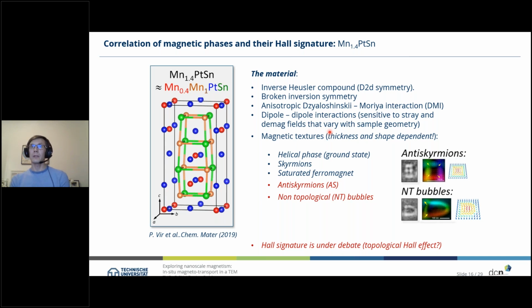So what makes it interesting for us, it hosts anti-skyrmions as well as non-topological bubbles, and especially the anti-skyrmions. For that, the Hall signature of these anti-skyrmions is still under debate, and this is due to the topological winding number of these magnetic textures, and I will come to that in a second.